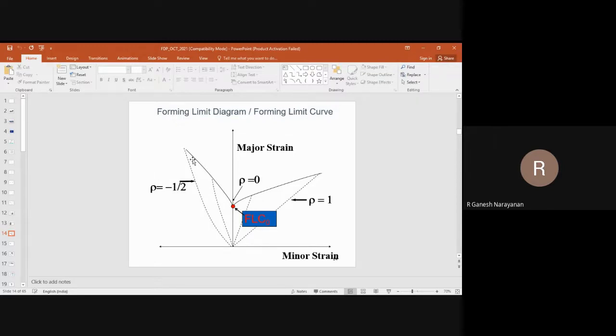Correct. Here also, as long as you are below the forming limit curve, any strain coordinate, minor strain, major strain, below the forming limit curve, is safe. That means you can deform the material easily without failure, below the curve. Once you reach this curve, it means that you have reached the limit of formability. Necking can start here. Above the curve, it is definitely a failure. And you can deform the material under various modes of deformation, various combinations of minor strain and major strain. That's why these dotted paths tell you. From left, you can see 1, 2, 3, 4, 5. 5 different paths are shown. It's referred to as rho, isn't it? These are different strain paths.